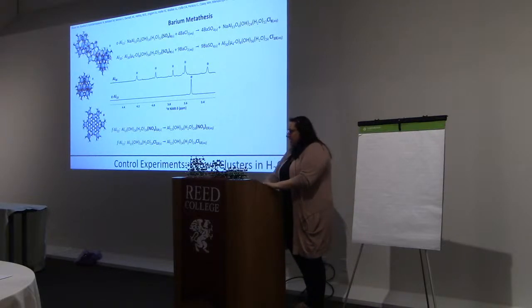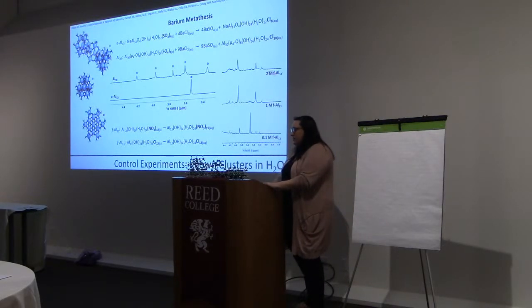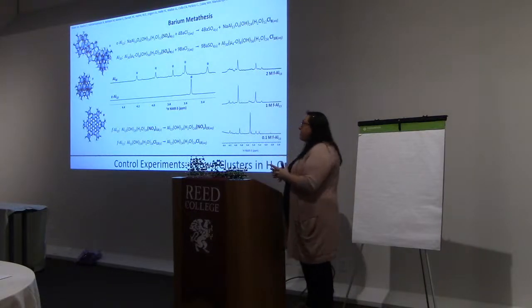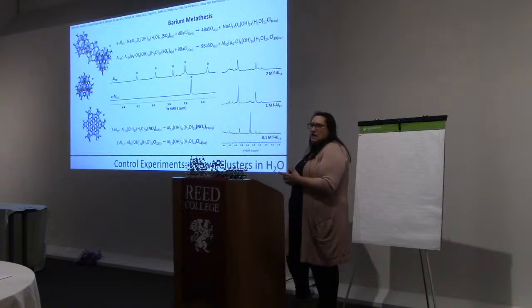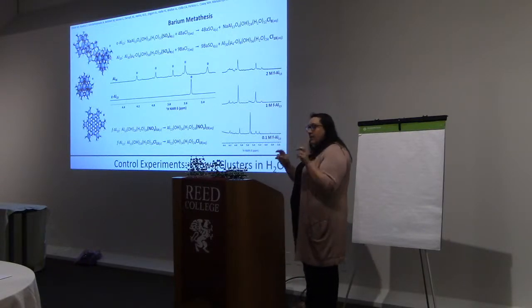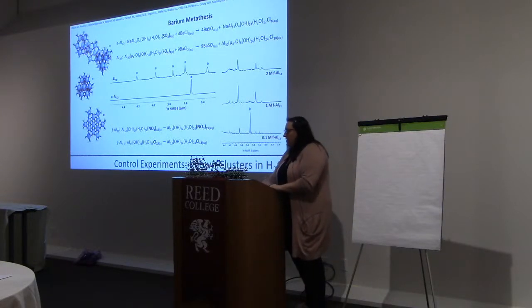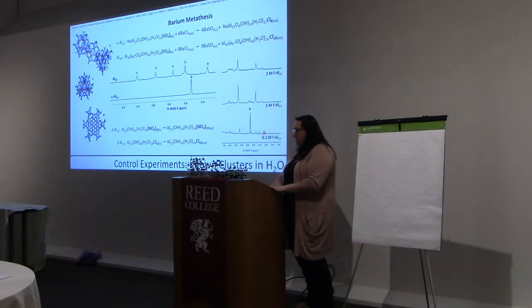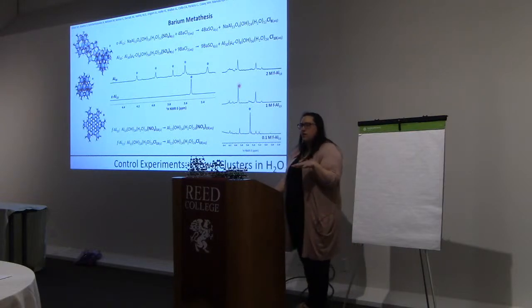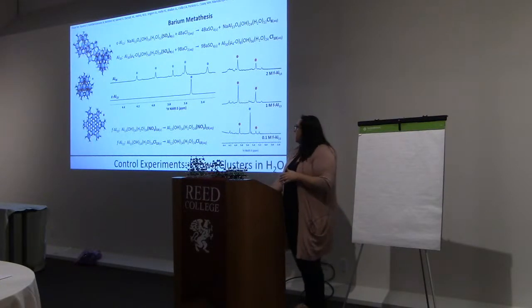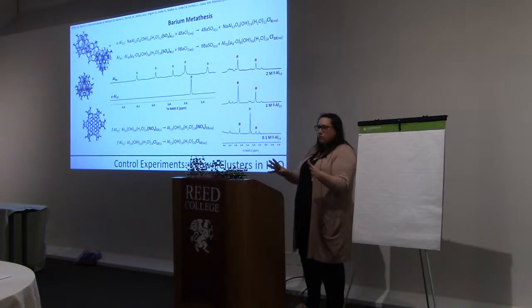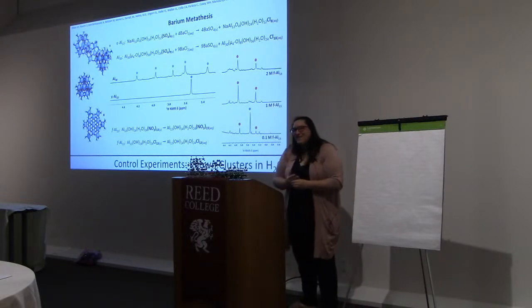When we dissolved these, I dissolved them with my students at 3 different concentrations, and we didn't see the exact same thing at our different concentrations, which made us a little concerned that it was going to be difficult to figure out our fingerprint region because stuff was happening as soon as we were dissolving this in solution. We saw that this large signal corresponded chemical shift-wise to our epsilon. And so initially at low concentrations when we dissolved this, there was epsilon in our sample. And then these 2 signals are pretty prominent in all the spectra, and we hypothesized that these were going to be the 2 signals that were our fingerprint of this flat cluster. But we wanted more evidence of that.